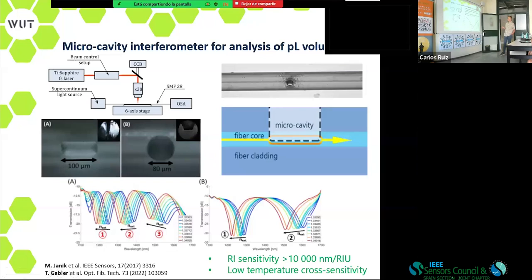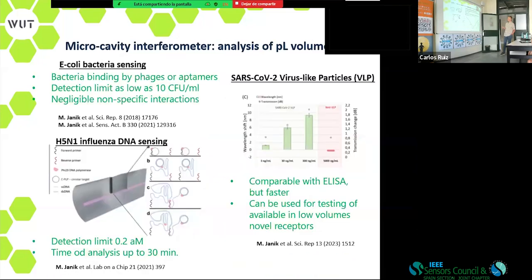it to our needs. So when something like this appears and we fill it with liquid, you can see that there is a huge sensitivity to the refractive index. So there's a beam that follows the core still, and part of it goes through the liquid, and the interference pattern obviously itself can be used for effective indexes, but it's not that interesting. We think that it's more interesting for biosensing.